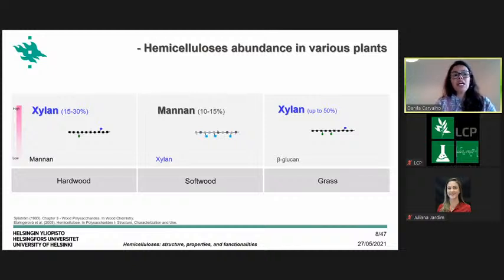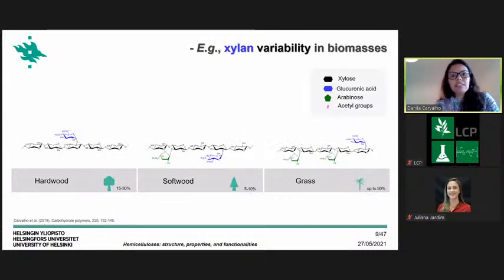And also it's important to know that even if there is one hemicellulose that's the most common in each of these biomasses, other hemicelluloses can still be present in the composition of such biomasses. If you just take as example the xylan, we can see that the structure of the xylan also varies between the different biomasses. Here you can see that the composition of the monosaccharides varies between the different hemicelluloses, and also the acetylation position and the acetylation degree can vary. And in the case of the softwood, the xylan in softwood, no acetylation is observed.